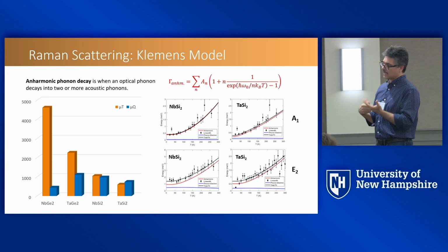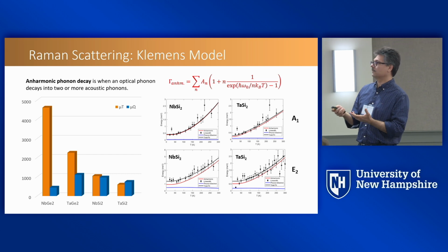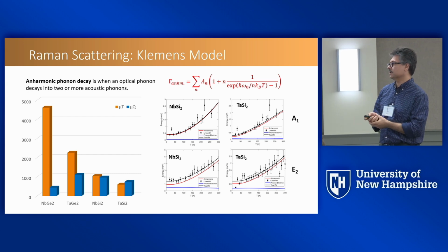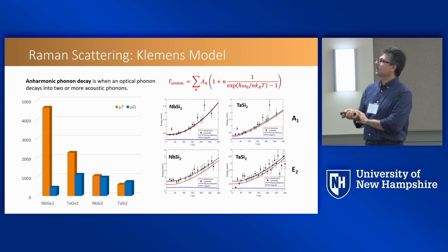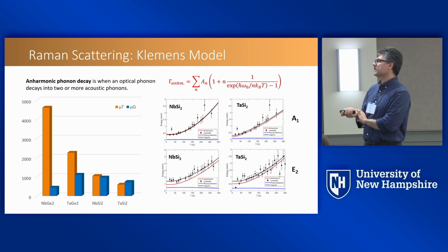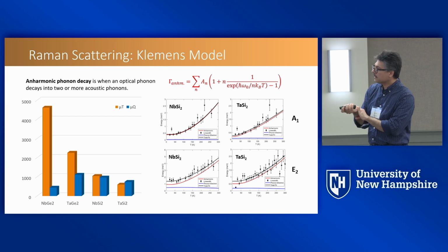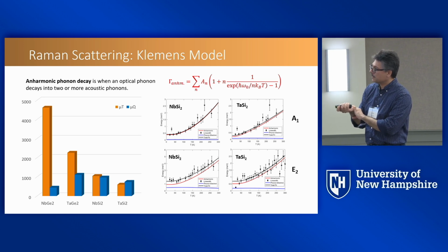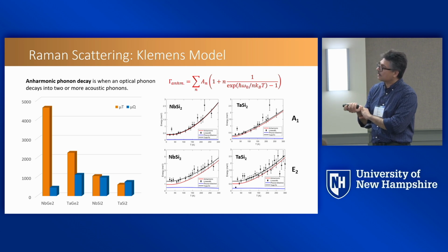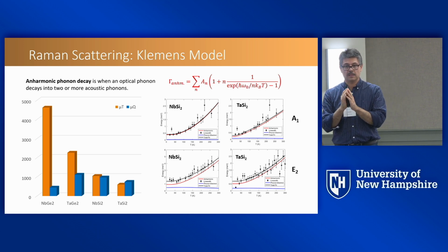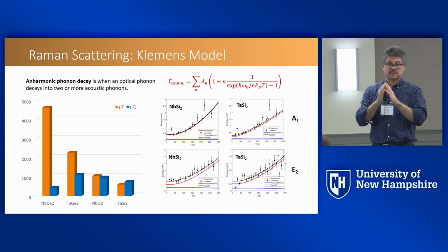And so we wanted to see what the electron-phonon interaction is in these systems and how that changes. For that, I collaborated with my colleague next door, Ken Birch. He measured the Raman spectra in these systems, and we looked at the temperature evolution of Raman peaks. And we found that there is a fundamental difference in the temperature dependence of Raman peaks between the silicides and the germanides. For the silicides, as we increase the temperature, the Raman peak line width increases. Basically, the Raman peaks become broader.